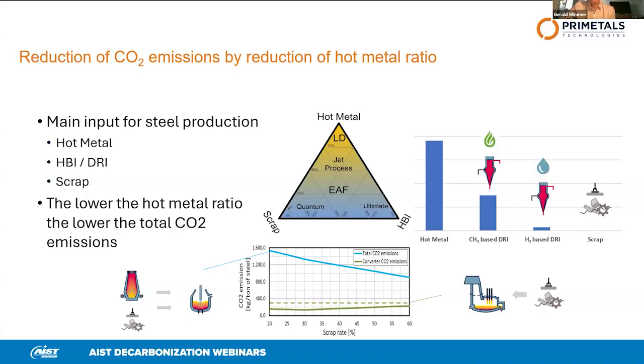And as you can see on the very right-hand side in this diagram, we see the typical materials that we can charge into the BOF converter, like hot metal, DRI, and the related CO2 emissions. And we see, as we already discussed, hot metal production in the blast furnace needs a lot of energy, which is mainly carbon. That's why hot metal has a lot of CO2 produced, compared to the scrap on the very right, which has zero CO2 footprint by definition. So by varying the scrap mix in the BOF converter, we can reduce the overall CO2 emission by reducing the hot metal ratio. And that is shown in the diagram in the center.